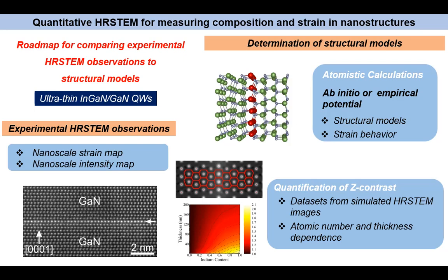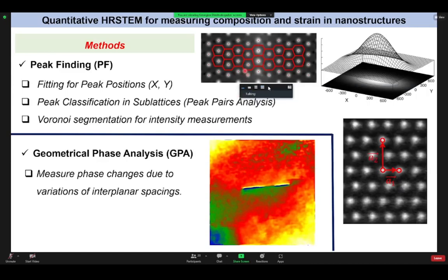What we do is that we ask the computer to identify the positions. It's doing some kind of fitting. Isaac will tell you more about this. It's fitting a two-dimensional Gaussian on each atomic position. Then it divides the space. It makes a tessellation, as we call it. It's called Voronoi segmentation, and then it calculates the intensity within each Voronoi cell.